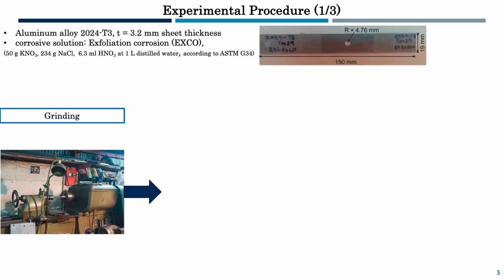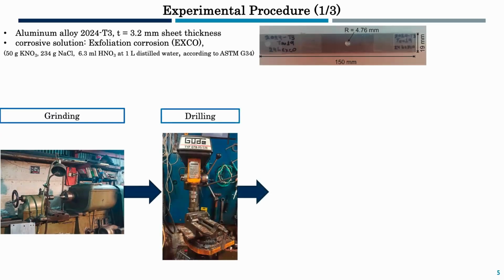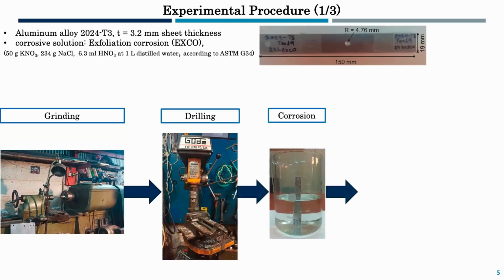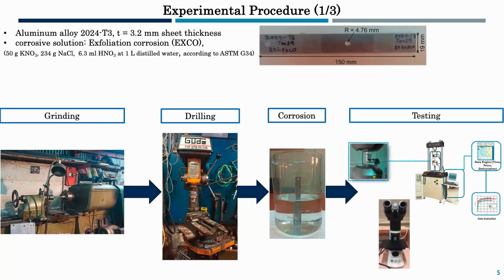In this work, as I already told you, the results for the aluminum alloy 2024 will be presented. The configuration of our specimens is shown in this slide, where a rivet hole of 4.76 millimeters in diameter was made. And the specimens were exposed to the exfoliation corrosion solution. So the experimental procedure consisted of the grinding of the specimens, drilling, corrosion exposure by simple immersion for several hours, and mechanical testing and microscopy.